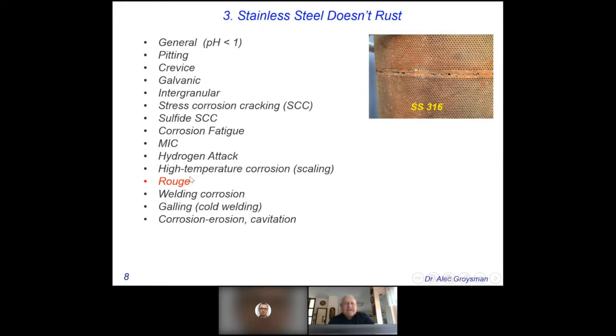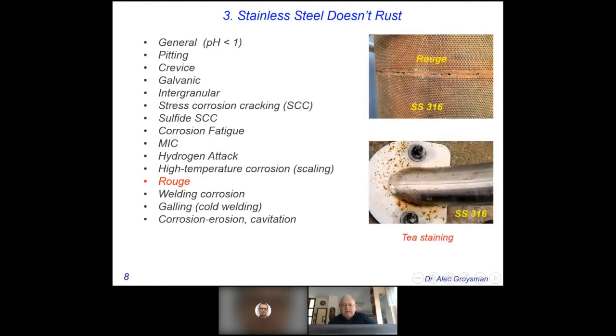The most interesting phenomenon is rouge. Sometimes these stains are named tea staining. You see here, stainless steel resists corrosion better than most other alloys because of a very thin, colorless passive layer that forms spontaneously on the surface. When the passive layer is breached, it usually forms again spontaneously.